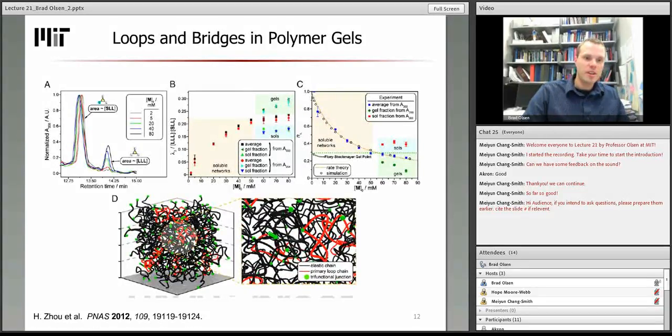So essentially, Jeremiah developed chromatographic and mass spec methods to isolate these different junction points after a network is degraded, measure their concentration, and then these can be compared with theories developed by Stepto, rate theory and Monte Carlo simulation, both of which are modified versions of Stepto's theories that we've implemented. And then these computations agree relatively well with theory. And so this actually provides a prediction for the chemical kinetics of network formation that appears at this level of comparison to be relatively accurate between experiment and theory.